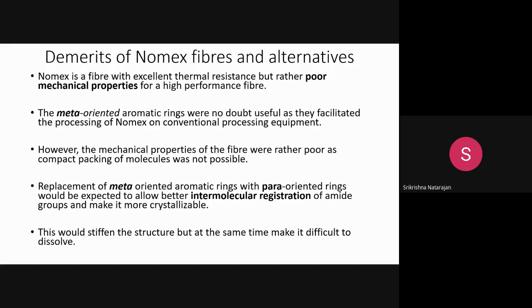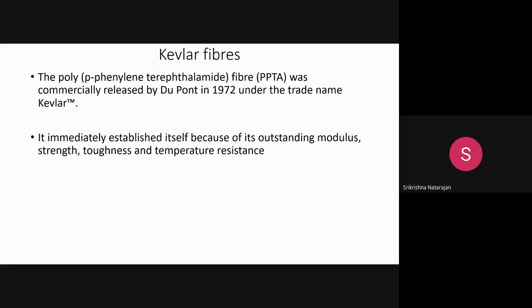Instead of using the meta-oriented structure, if we change it to a para-oriented structure, that will lead to more intermolecular hydrogen bonding, so that the fiber will be more crystallizable. So that is the reason why these meta-oriented aromatic rings were changed to para-oriented aromatic rings by using some different precursors. Instead of using a meta-oriented precursor, we use a para-oriented precursor, so that will lead to more intermolecular registration of the amide groups and make it more crystallizable, so that will stiffen the structure. Also, it leads to good mechanical properties. So that is the alternative, where the change is from meta to para. So that is the Kevlar fiber.